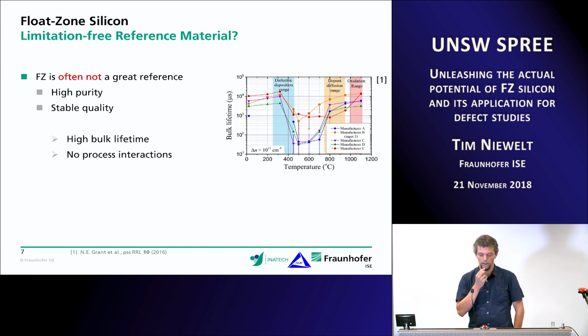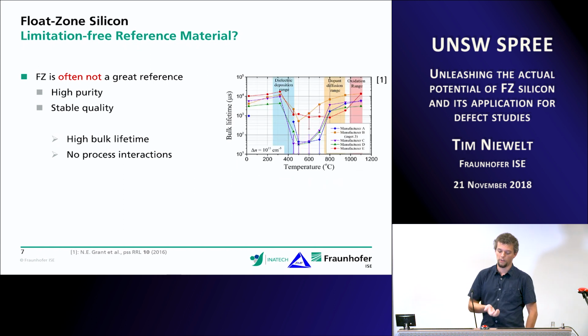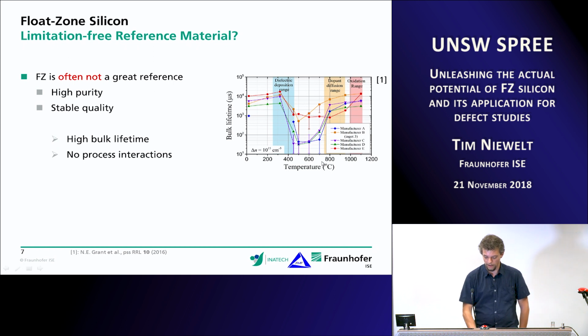And we dug deeper into that, and we found that other groups had seen that too. So here is a by now quite famous graph from Nicholas Grant, from a paper that he did, where they subjected float zone wafers of different manufacturers to thermal treatments at different temperatures. And as you can see, there is a certain temperature range in which the lifetime just drops. And some of these wafers are mostly dead lifetime-wise.